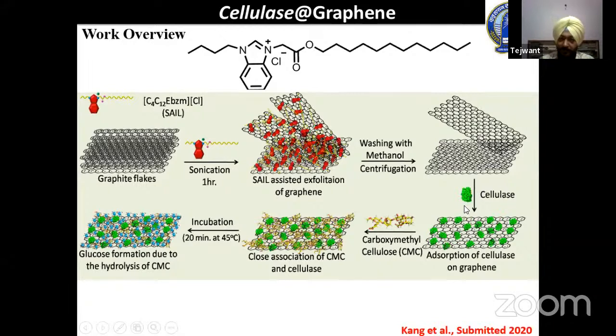So the enzymatic activity of this cellulase when present on the surface of graphene has been investigated for the conversion of carboxymethyl cellulose, which has been used as a substrate. It has been found that the cellulase is much more active as compared to that found in the buffer. So once you combine the enzyme cellulase with graphene, the combination shows much higher enzymatic activity as compared to that shown by the bare cellulase in the presence of buffer only.